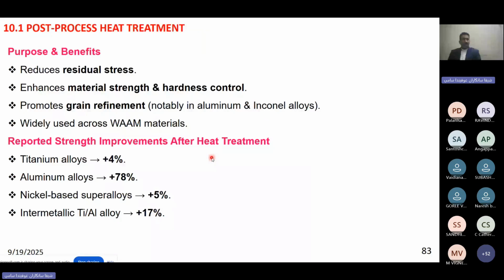That's post-process heat treatment. Many authors, I read some articles. For example, after heat treatment, 4% of strength was improved for one material, 78% for aluminum alloy, and 5% for nickel-based alloy. So you see the improvement of properties after the post heat treatment. The purpose is, of course, to reduce the residual stresses, improve the mechanical strength, ductility and hardness, and refine the grain structure. Obviously, the strength of the WAAM product will be improved a lot. This is one method.